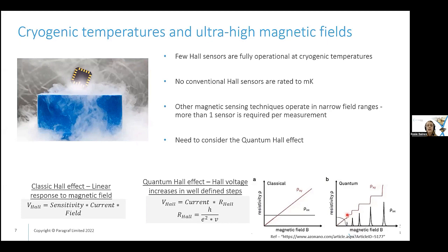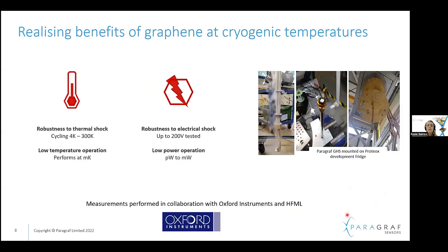So we have tested our graphene Hall effect sensor under a range of these conditions. Just some of the immediate things that spring out of it are just generally looking at the robustness of the sensor. You can see from these images here, here's our sensor mounted on the end of a probe, just there in its package and exposed to these extreme conditions. So we saw robustness to thermal shock during cycling between 4 Kelvin and 300 Kelvin, as well as very low temperature operation, so working at millikelvin temperatures, and that's something I'll come on to in the next few slides as well.